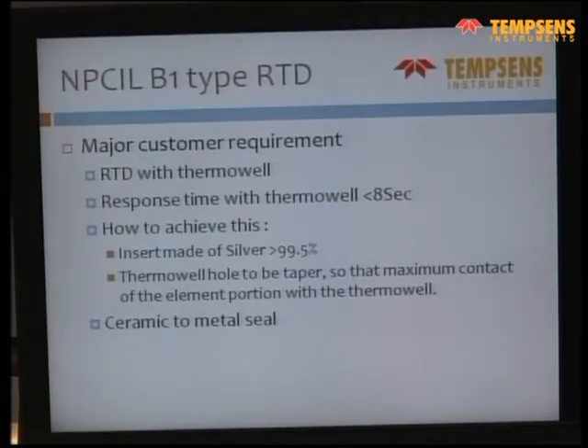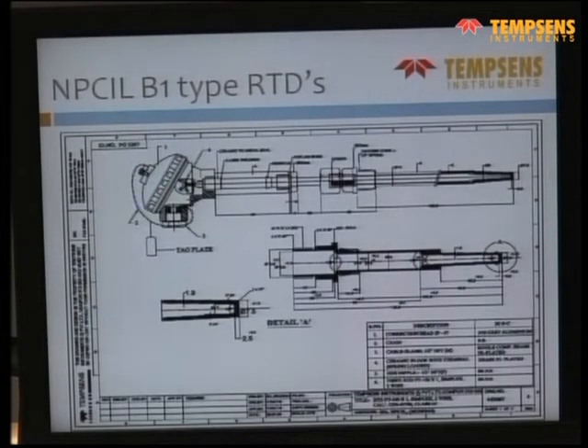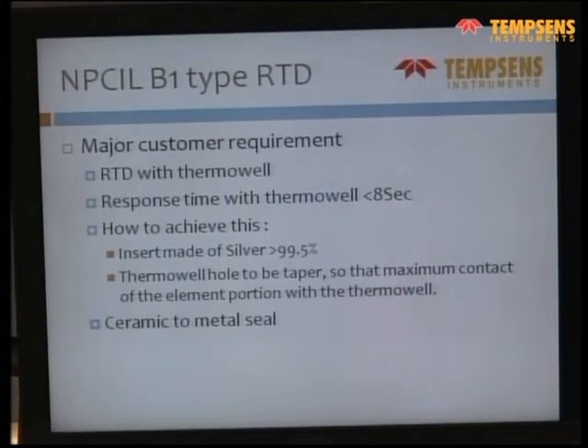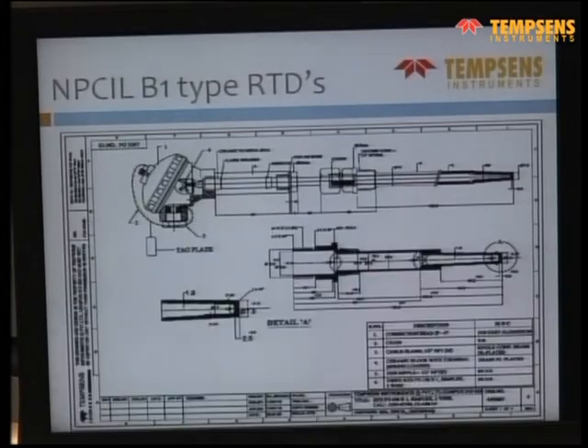There is another type of RTD for NPCIL in which the response time required is less than 8 seconds. We saw this a few slides back. Here the insert was made of silver and the thermowell was tapered so that you have the maximum contact for an RTD. And they want the life to be more than 20 years. So each RTD is with ceramic to metal seal. It's not just general epoxy with which we are sealing the cold end.